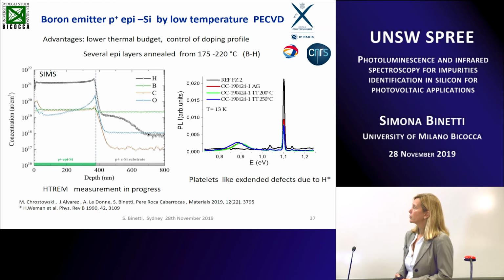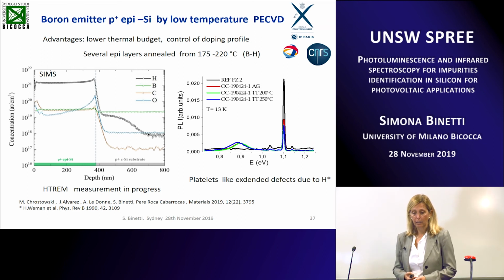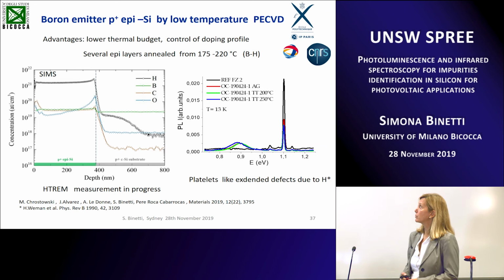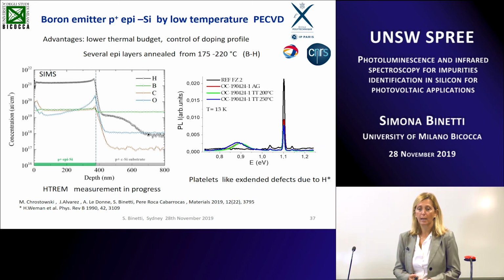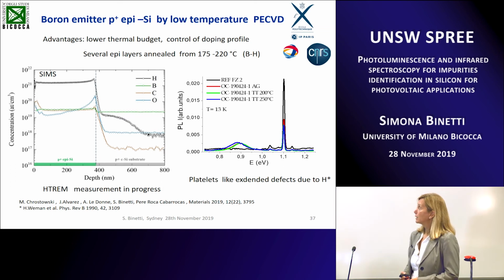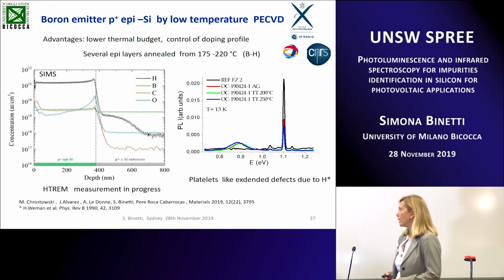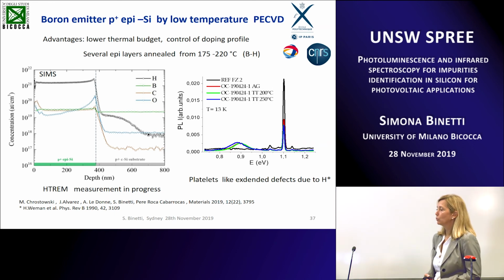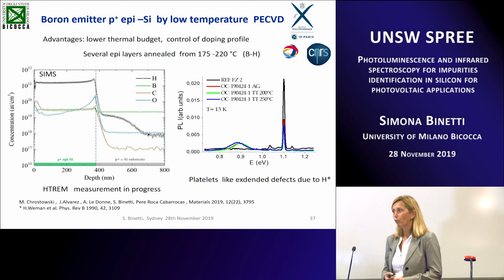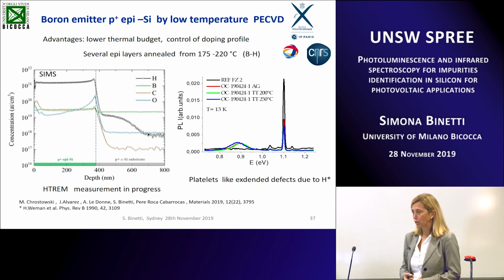And so we decided to study with them the presence of any defect by photoluminescence and also by infrared spectroscopy. We have seen a lot of silicon-hydrogen related vibrational modes due to the high concentration of hydrogen. So you can use infrared instead of SIMS in order to detect the hydrogen concentration. But we have seen this broad band that is not related to oxygen precipitates, it's not related to dislocations, but in this case is related to an extended defect that is formed due to the high concentration of hydrogen. This has been work that was done many years ago.